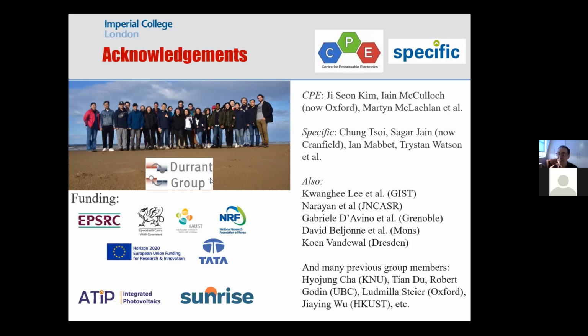Oh, yes. I mean, DSCs, the model uses a donor bridge acceptor model. Yes, that's certainly true. And that is one way to help separate the charge. The beauty of dye-sensitized solar cells is that we can orientate the dye molecules on the surface. And so we know which direction the dyes are pointing compared to the titanium substrate. In the organic solar cells, it's much, much harder to orientate one molecule relative to the interface. And that makes this idea of a donor bridge acceptor molecule, which was very good at separating the charges in dye cells, much harder to apply to the organic solar cells. I hope that helps at that point.